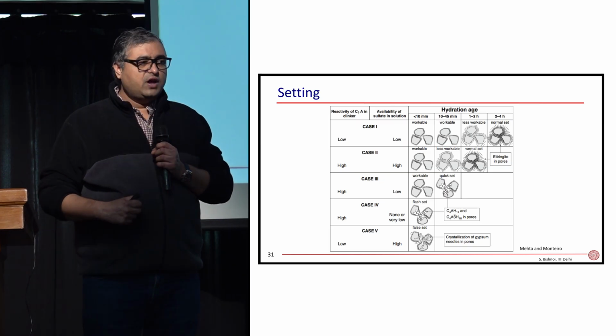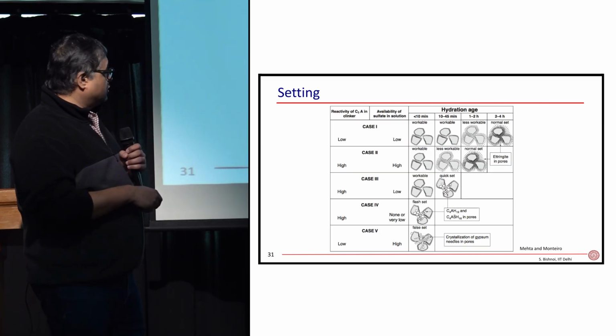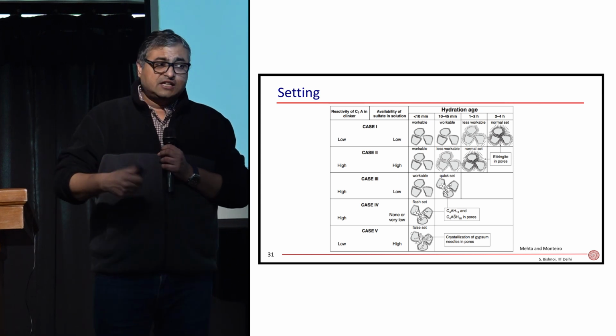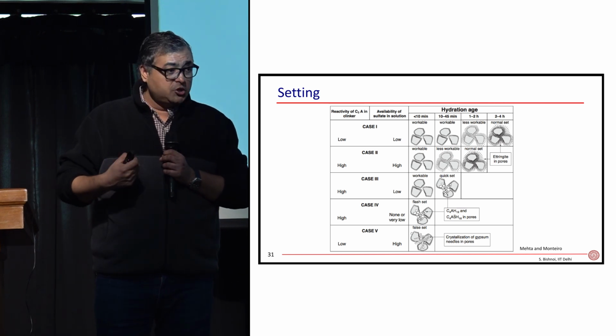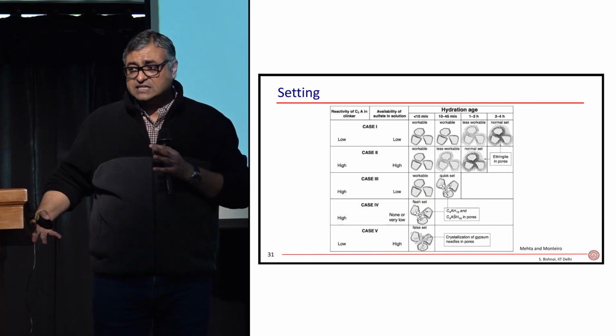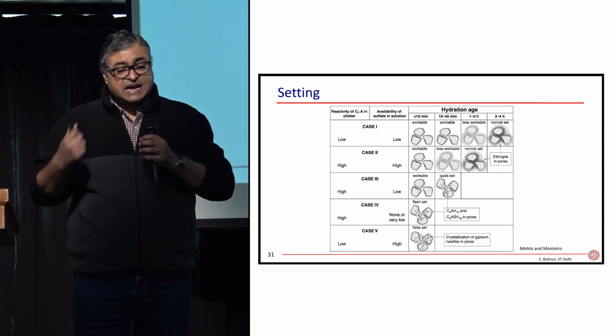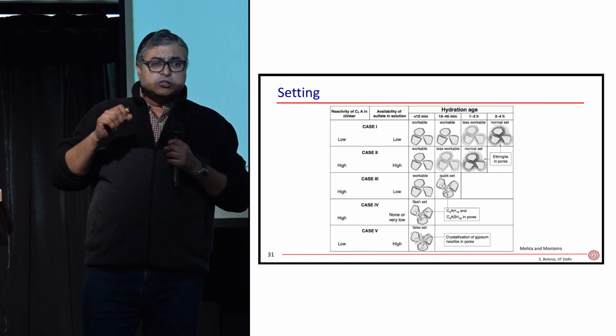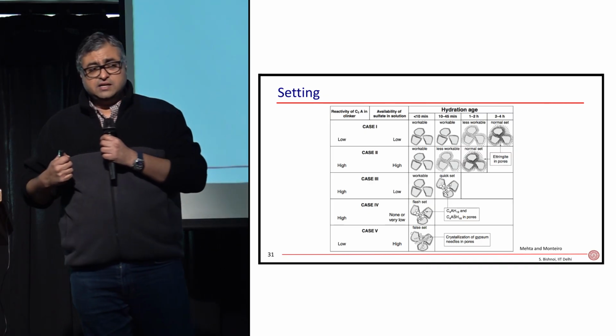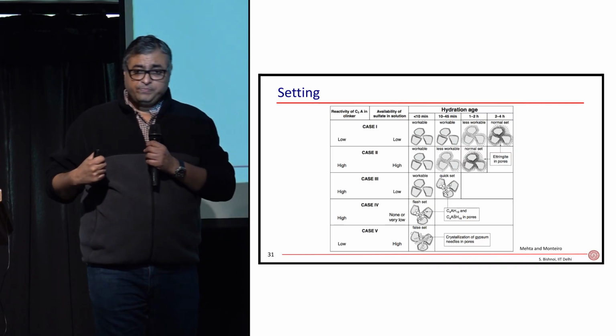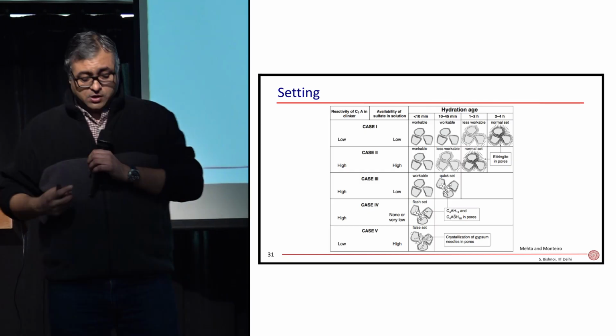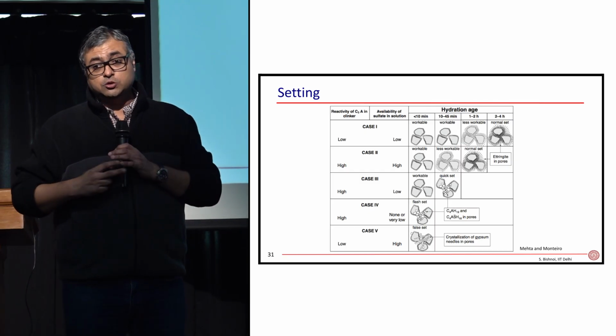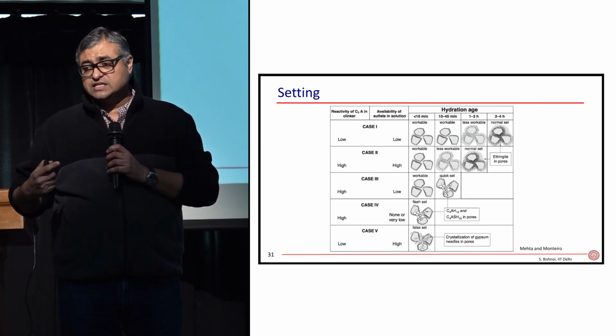If you have too much gypsum, what may also happen is when you're mixing the concrete, the gypsum will dissolve in the water. The moment you stop mixing, the gypsum precipitates and creates crystals, and these crystals hold the cement together. So the thing holding the cement particles together is not a product of hydration, it's the precipitate of gypsum or sulfate, and that leads to a pseudo, or what is known as a false set.